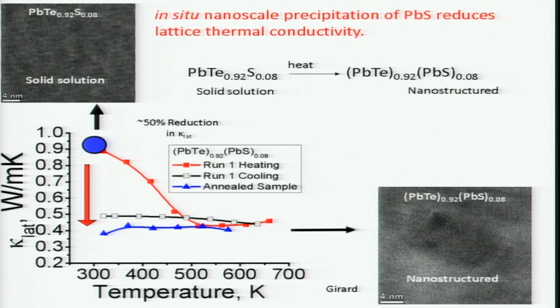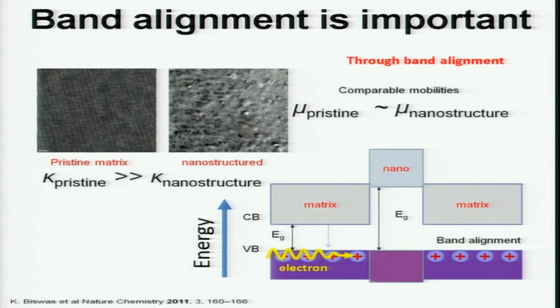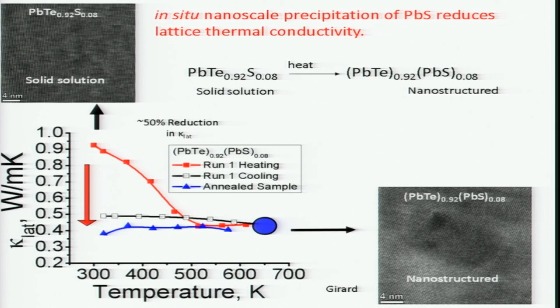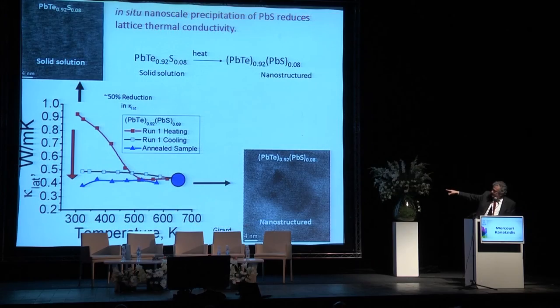You see it in this plot, the blue point is the thermal conductivity 0.9, so it's already very low, 0.9 watts per meter Kelvin. That corresponds to the solid solution above, the homogeneous sample. Then we start raising the temperature, we precipitate the nanocrystals, and the thermal conductivity collapses down by 50%.